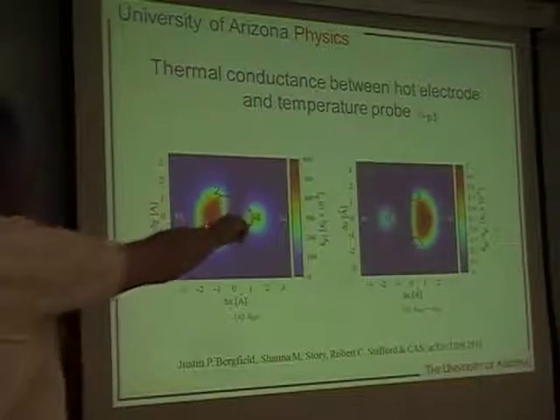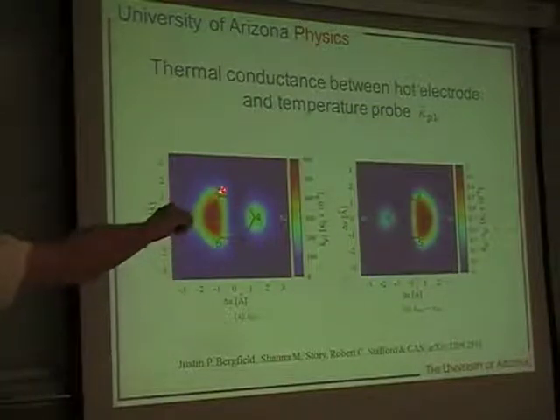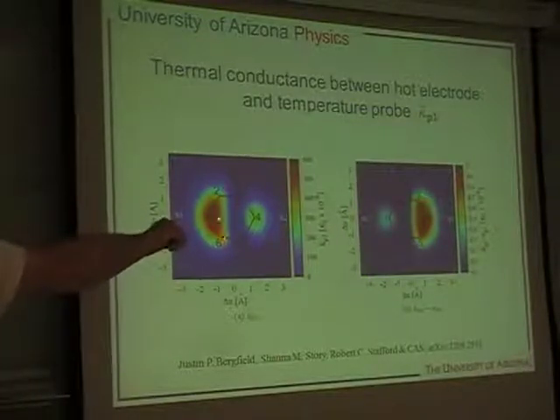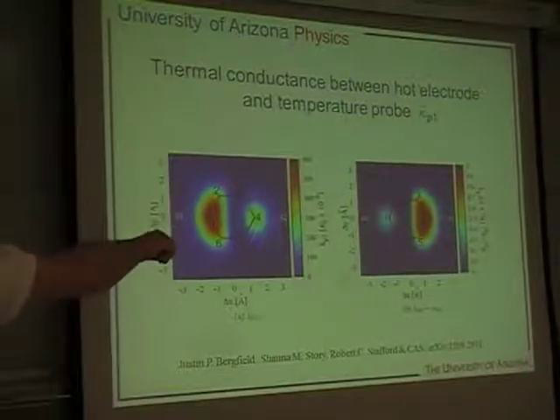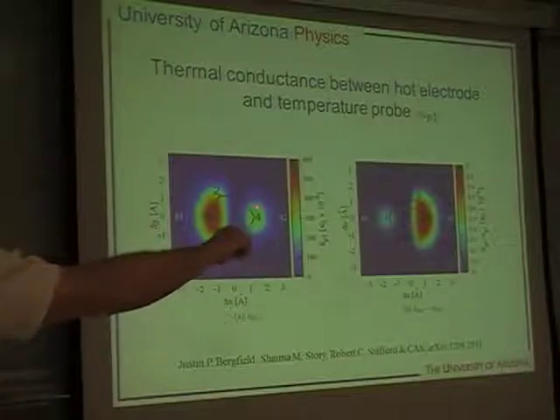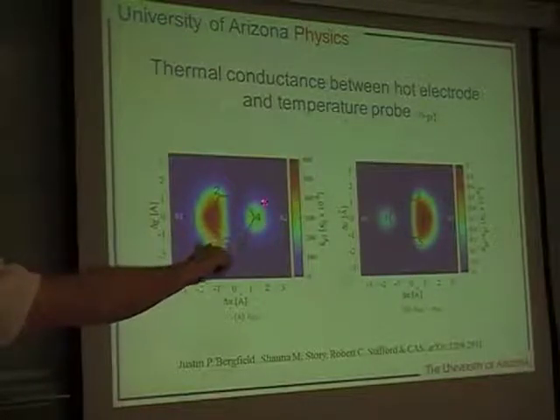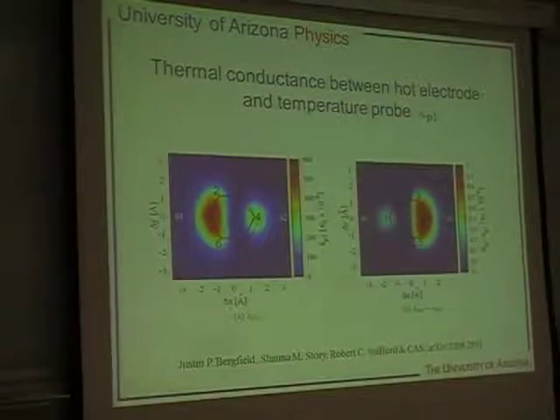a large thermal conductance. When it's over this orbital, which are in an ortho configuration relative to the hot electrode, there's also a large thermal conductance. And when the temperature probe is over this orbital, which is in a para configuration relative to the hot electrode, there's also a large thermal conductance. However, if the probe is over this orbital, the thermal conductance is essentially 0. So electron waves simply cannot get from here to there or from here to there.